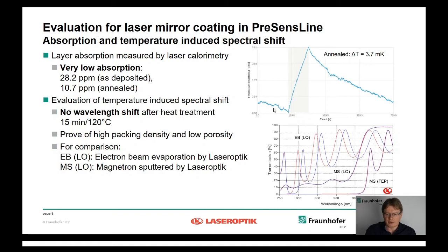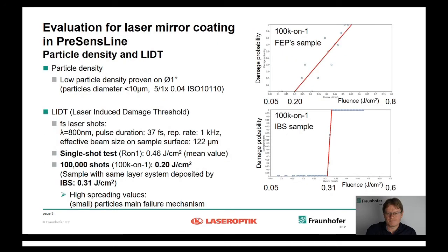And they also deposited a layer system by electron beam evaporation, and here they observed a quite high shift. With Magnetron sputtering, our system had, we could prove, a high packing density and low porosity. The particle density was low. This was evaluated by Laser-Optic, and they could prove that the largest particle diameters are below 10 micrometers, and we met this ISO standard.